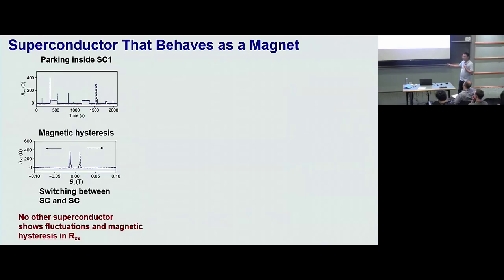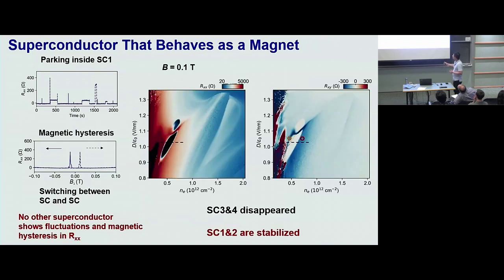If you scan outer plane magnetic field, you get the spikes separating 2 states that both have zero resistance. So this magnetic hysteresis is between a superconducting state and another superconducting state. No other superconductor does this. This is a fluctuating superconductor. And when you apply a 0.1 Tesla outer plane magnetic field, you get phase diagrams like this.